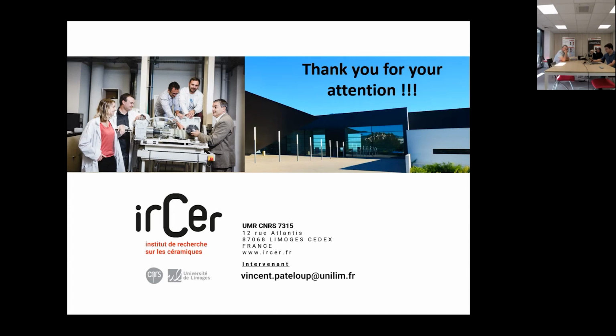Thank you, Vincent. Another question from Tang J. May I ask if the current printing time is still relatively long? And is there a way to shorten the molding time? Concerning the SLA process, the time is the same as for a normal part. And concerning the metal deposition, it really depends on the volume of metal that is deposited in a slice. If it's only a track, we don't have to wait for the drying of the metal paste, and we can then print with times that are near classical printing times. If we make a mass plane, as I have presented with the microstrip resonators, we have to wait for too long a time for industrial application today, I think.